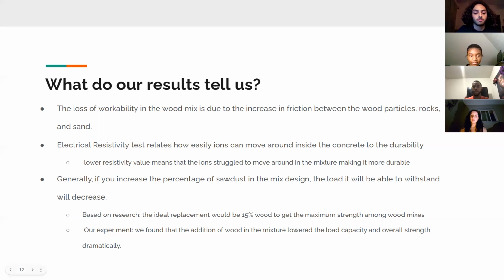Our experiment results, we were limited on time, and we also struggled to get the mix weights in order. So it was tough to get a third mixture or a fourth mixture with higher wood percentages into molds. It would have been nice to test a 2.5, 5, 7.5, and 10% mix to determine which would perform the best. According to some research that our group did, the ideal replacement would be 15% wood to get maximum strength among the wood mixes, but less than an 8% addition of wood would be the most ideal for retaining all the important properties of the mix, and that would ensure an increase in durability, but decreased workability and compressive strength.